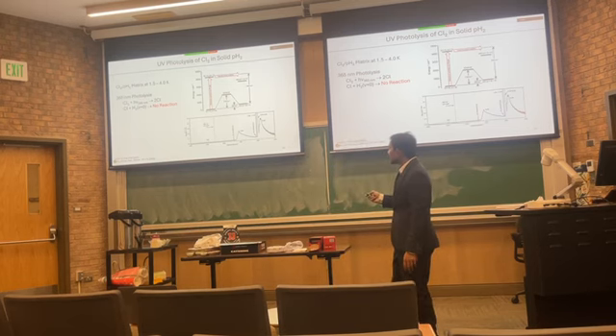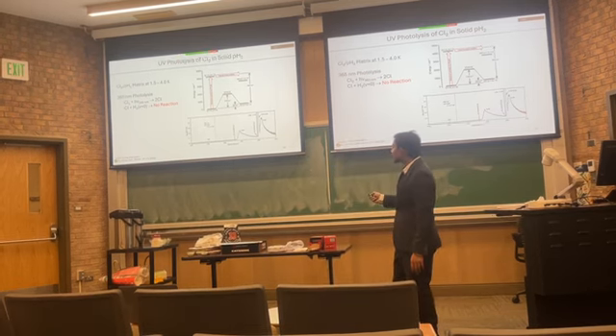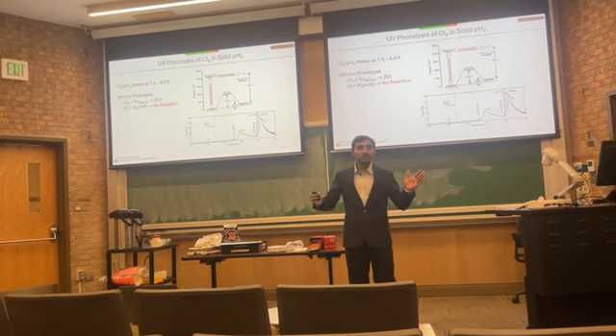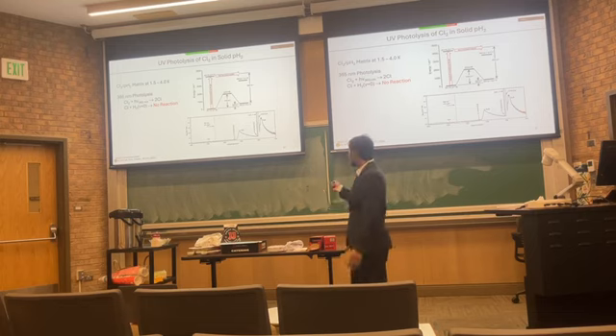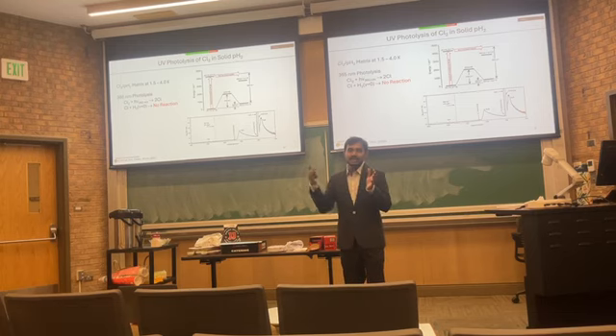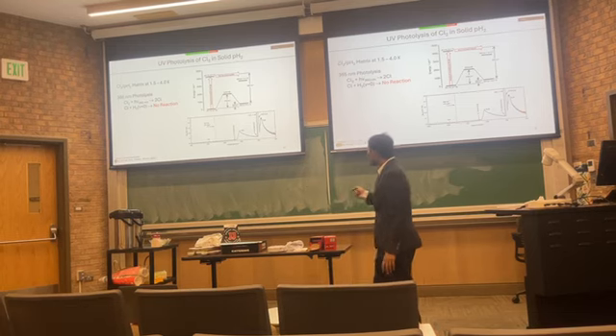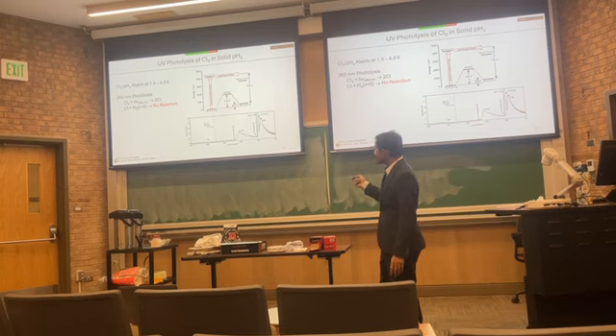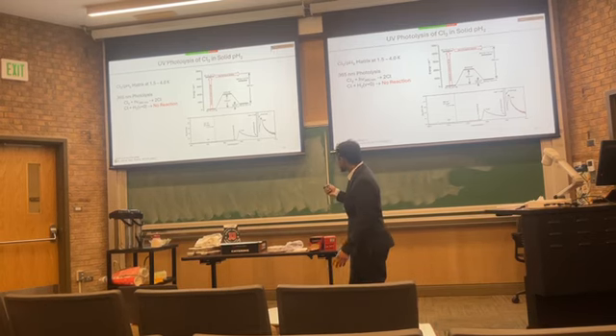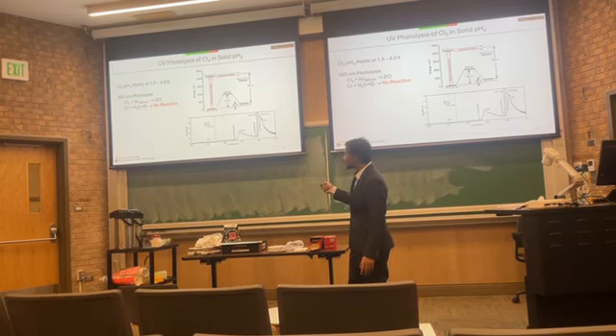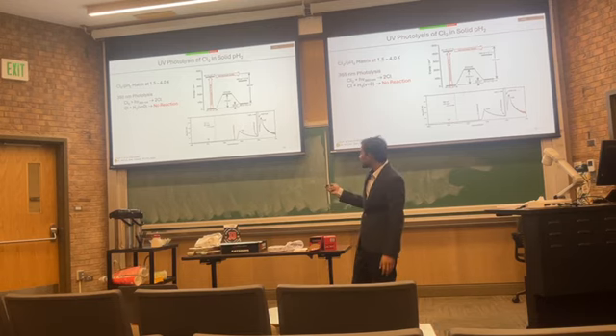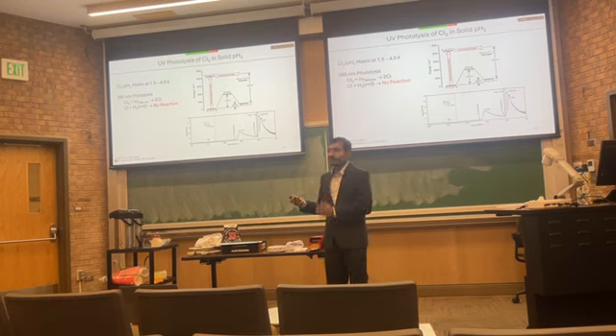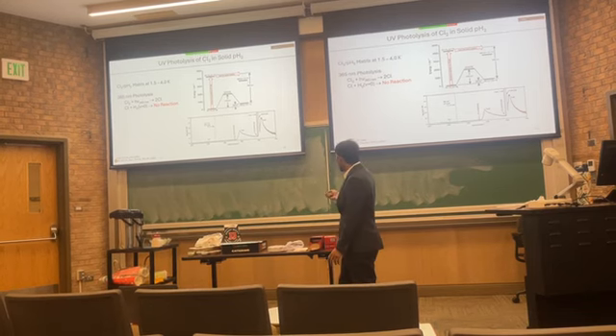We use near infrared light. Hydrogen absorbs at 4100 to 4500 wave number. So if you put that energy, those infrared lights, onto your matrix, you excite the hydrogen and this reaction will happen. But if you block them with a filter, we call it LPF, low pass filter, and block all this near infrared, then this reaction will not happen.